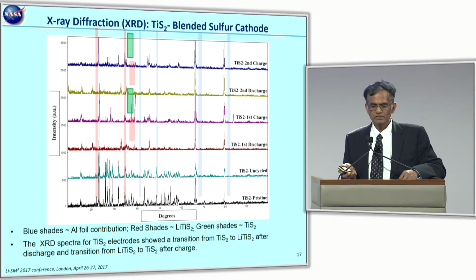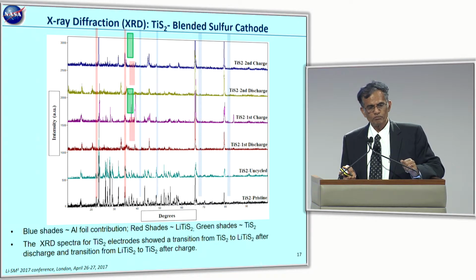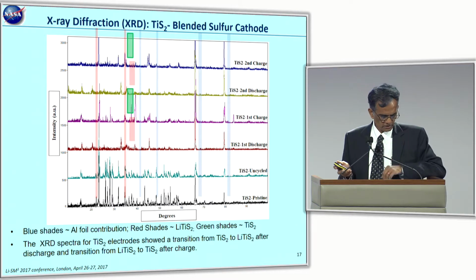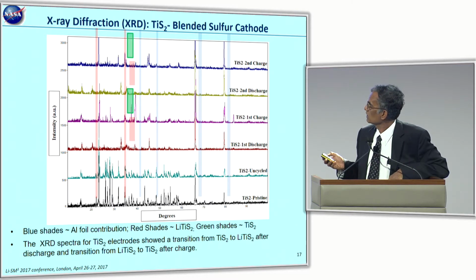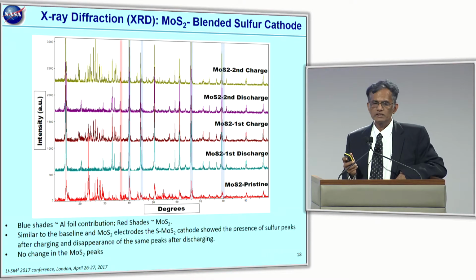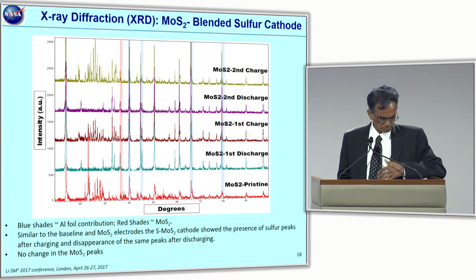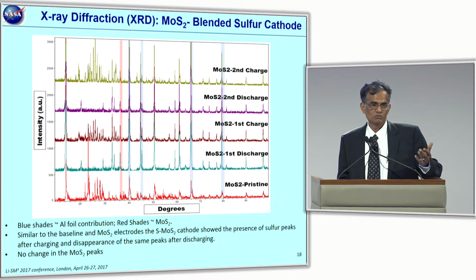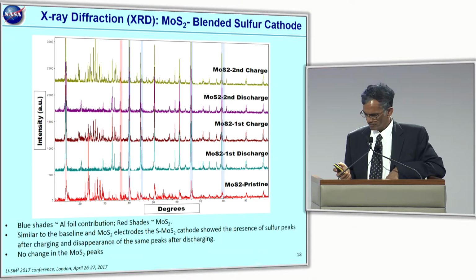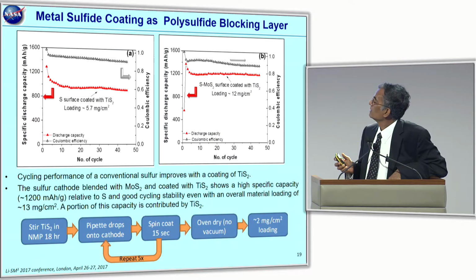So it is indeed participating in the reaction, and quite possibly it's helping mediate the kinetics of the sulfur cathode. Unlike TiS2, a similar set of data with moly surprisingly shows that there is no change at all in the moly. There are no lithiation and delithiation phases here. Interestingly, the effect of blending the sulfur cathode with this metal sulfide is as good as with TiS2, but there is no contribution per se in terms of capacity from moly here.